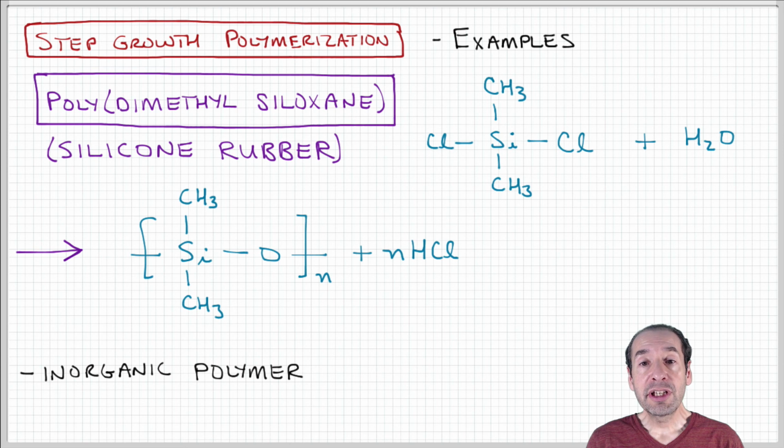So this material or this class of materials is known as silicone rubber. If they're cross-linked in particular, they have properties where they can be deformed and then they'll recover their shape very easily. They also have favorable properties because they're chemically inert and good thermal insulators. So they're used in a lot of applications for heat insulation or encapsulation of electronic products.